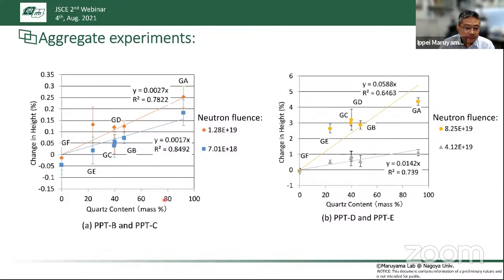And this is the data of the aggregate expansion as a function of the amount of alpha quartz with different neutron fluences. The blue, orange, gray, and yellow are different neutron fluence levels. As you see, at the low neutron fluence level, the expansion of aggregates is almost linear to the quartz content. While in the higher neutron fluence cases, a fluctuation was confirmed like this. This indicates that rock-forming minerals other than alpha quartz are possibly also affected by the neutron irradiation. That is why we see this kind of fluctuation here. But in the case of lower fluence, the impact of alpha quartz is quite large.